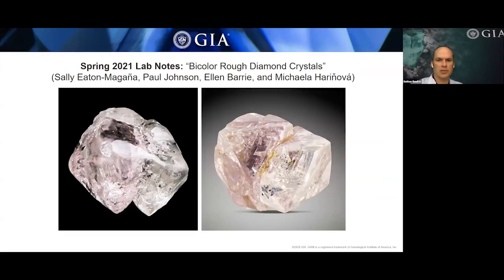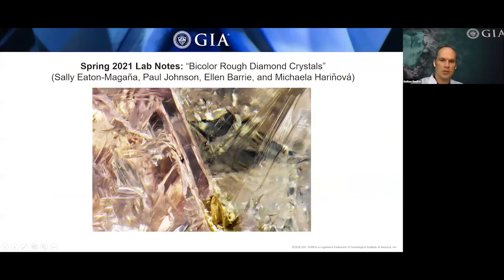Another interesting note is there was a pair of bicolor diamond crystals that came through the laboratory. Bicolor diamond crystals are pretty uncommon, and so to have a pair of bicolor crystals was quite unique. And so in one of the crystals, you have a very strong pink coloration, and in the other adjoining crystal of each of these two pairs, the crystals were colorless. You can see clearly the boundary between the two crystals. The crystal on the left is very pink, and the crystal on the right is essentially colorless.